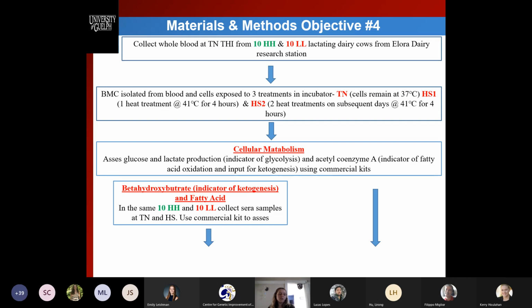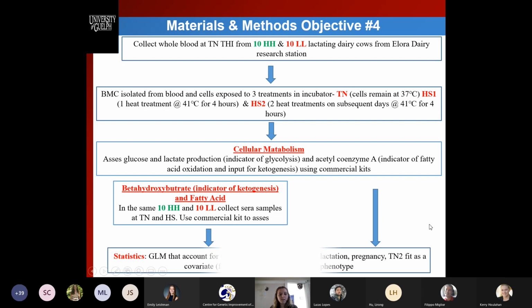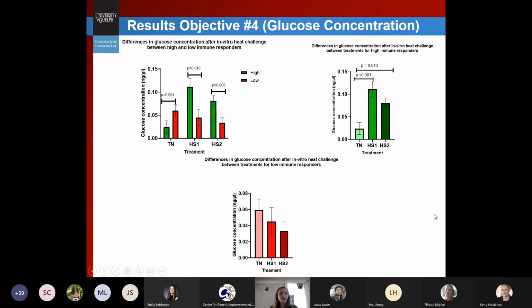Typically, during a non-stressful event or possibly at thermoneutral conditions, immune cells will use the oxidative phosphorylation cycle in order to produce energy. However, during possibly heat stress or a stressful event like disease, there's no longer enough oxygen available to use the oxidative phosphorylation cycle to produce energy. So studies have shown that typically immune cells will switch more to the glycolysis cycle to produce the energy needed during those stressful events. Okay, so to analyze this data, we used general linear models. Now I'm going to move on to talking about the results from this study.